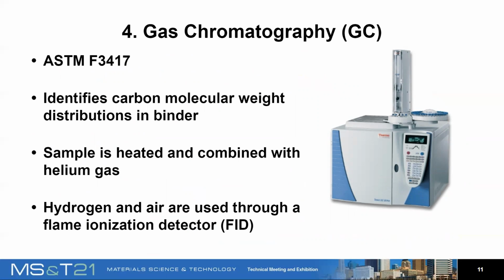Now, moving along to gas chromatography, also known as the GC. The GC allows us to identify carbon molecular weight distributions within the oil or wax binders. This is done by using a flame ionization detector to break up the molecular compounds. The amount of paraffin wax in the binder can generally correlate to the track's mechanical properties, but species with lower molecular weights will have more fluid-like properties at room temperature when compared to their more complex structures.